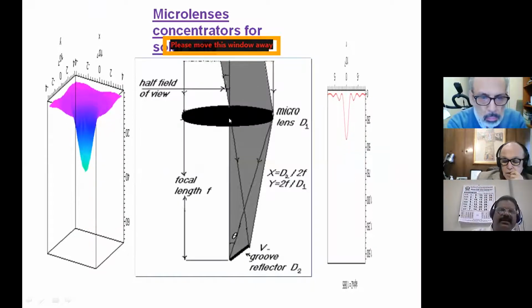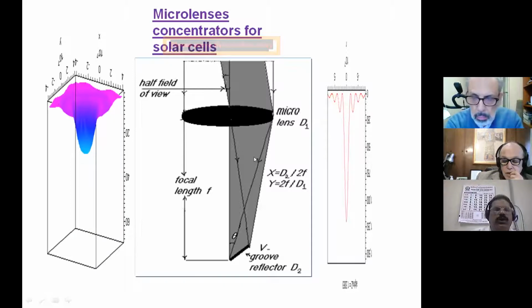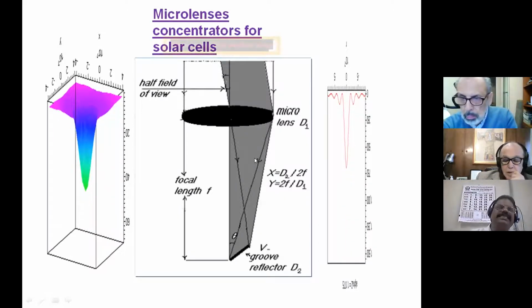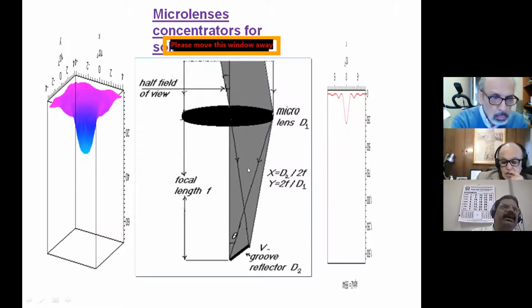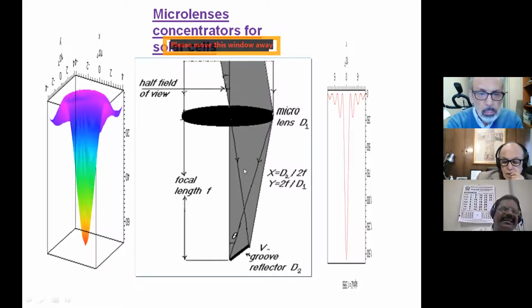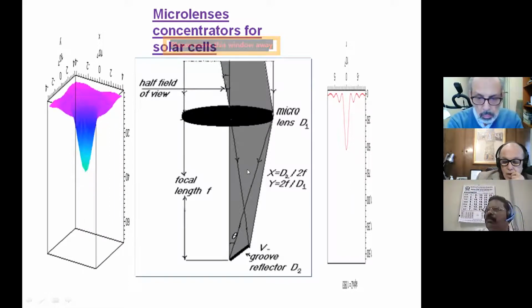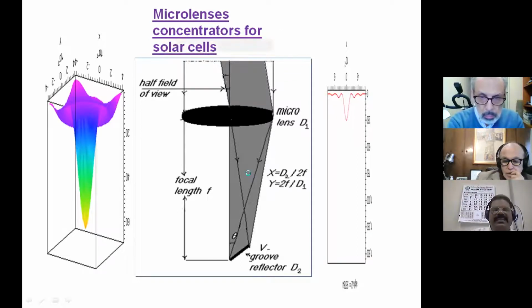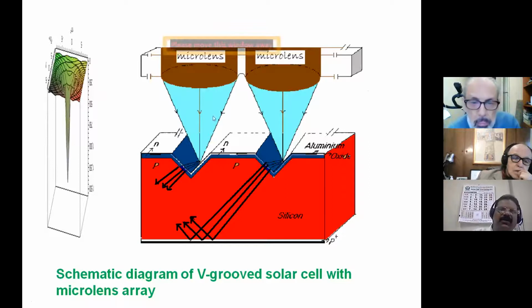So according to our geometry, we can reshape the structure. This is nothing but ethyl vinyl acetate used as a base to combine the V groove structure and micro lens. Why we are using ethyl vinyl acetate is that there is no change in the refractive index of the material medium. Both the EVA and the micro lens have the same refractive index. In this way, we can arrange or align the micro lens above the V groove structures, so that we need some mathematical expressions which we have already discussed.